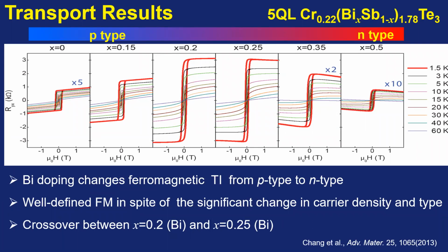We can see when we tune the bismuth doping, the ferromagnetism is always there. So the ferromagnetism can survive in both P-doped and N-doped chromium-doped bismuth antimony telluride. This is very good news. You know, in diluted magnetic semiconductors, the ferromagnetism is usually achieved in the P-doped sample. When you tune the sample to the insulating regime or to the electron-doped regime, the ferromagnetism will disappear.